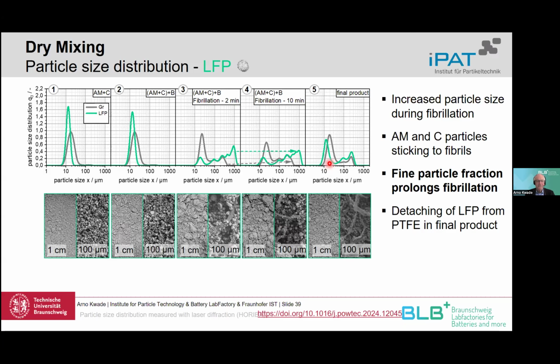Maybe also looking here for the LFP, it is the same, no change in the particle size distribution. Then we have really a lot of big granules after starting the fibrillation, and also you see really big granulates still after the end of the fibrillation process. But then for the final homogenization, we come again to smaller granules, which we need for the coating process, and it's a little bit more granules, but also finer material. So these are the original primary particles which are not granulated, and these are the granules. So we have a mixture of, let's say, free particles and particles which are detached, which are sitting on the fibrils.